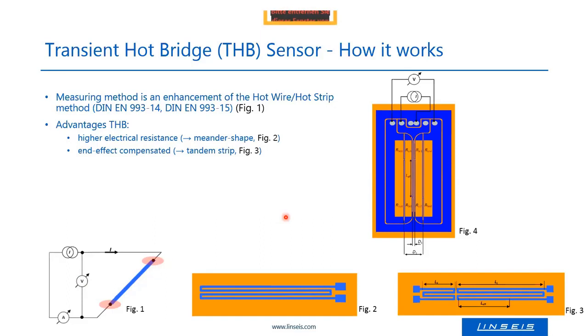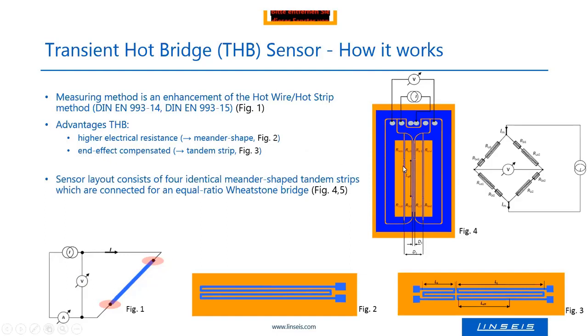And to get rid of this zero calibration in measurement techniques, it's a good thing to apply a so-called Wheatstone bridge. So we have here four wires and we connect them to a Wheatstone bridge with four resistances, 1, 2, 3, 4. And the measurement is the diagonal voltage of this bridge. And it needed to be equilibrated in former times.